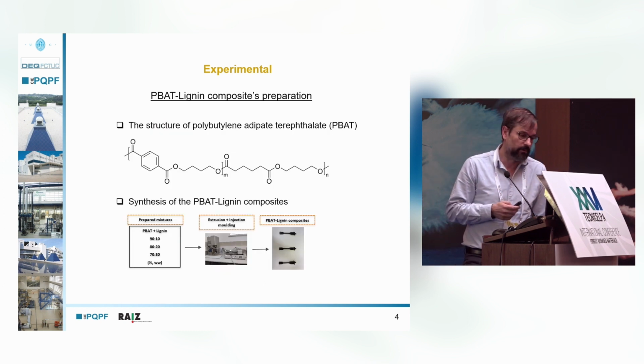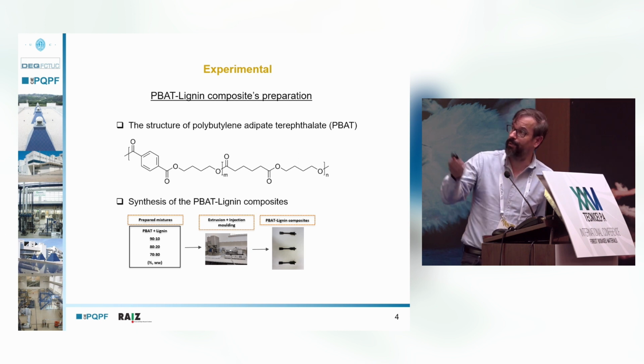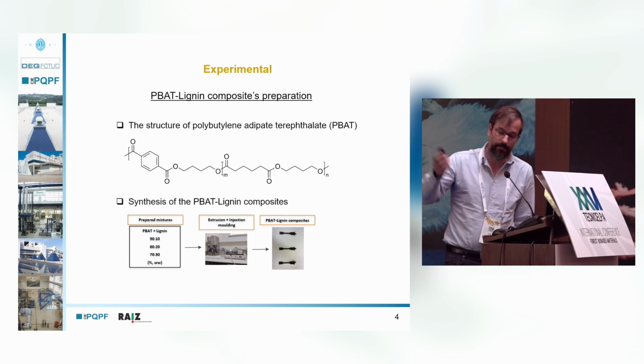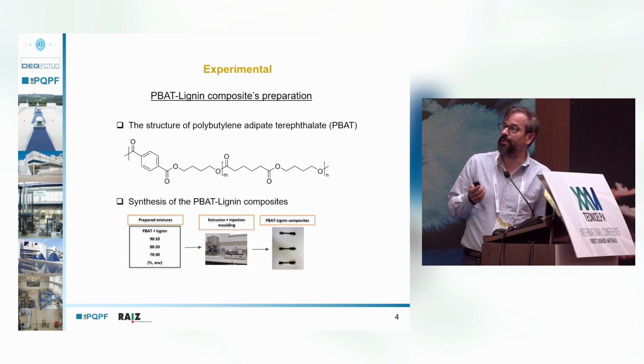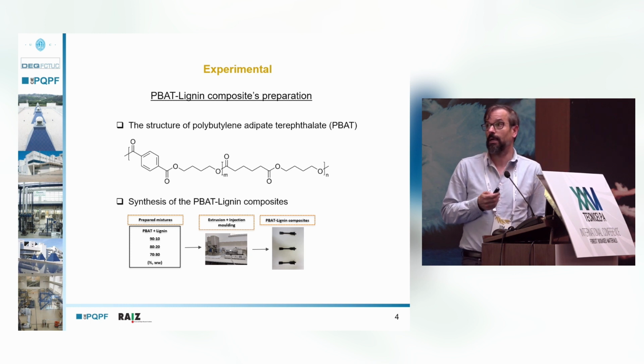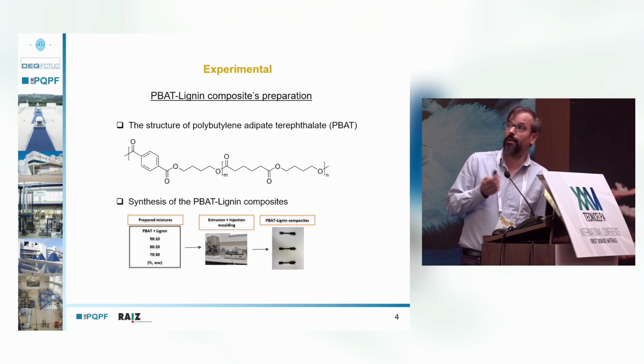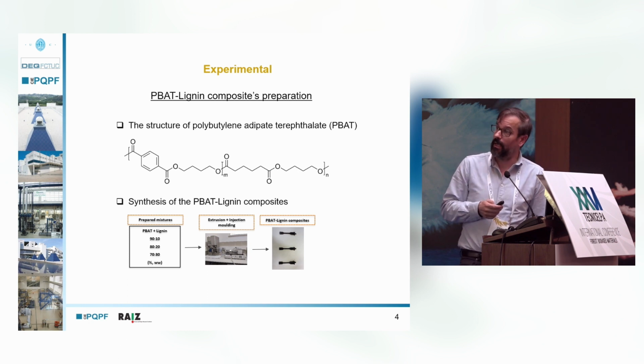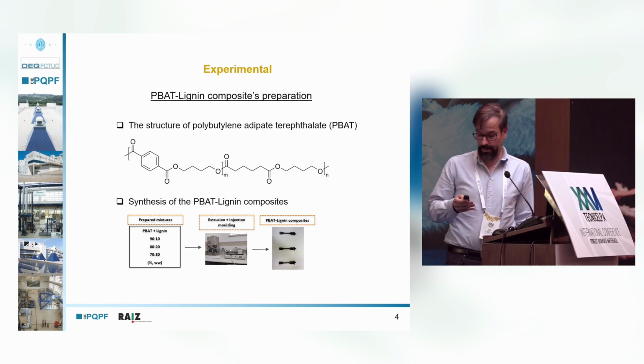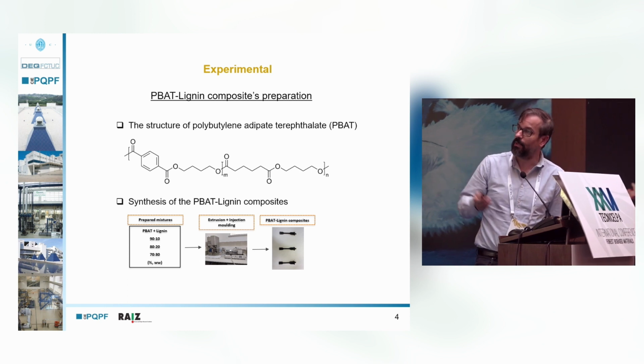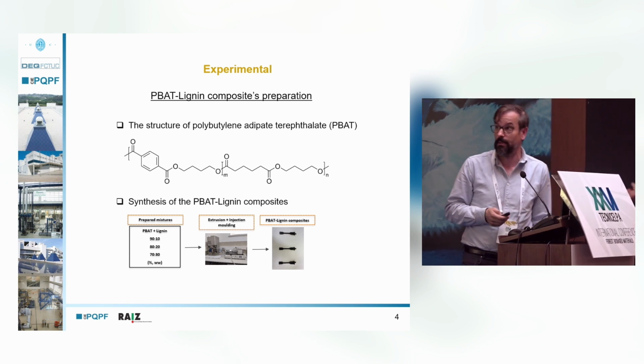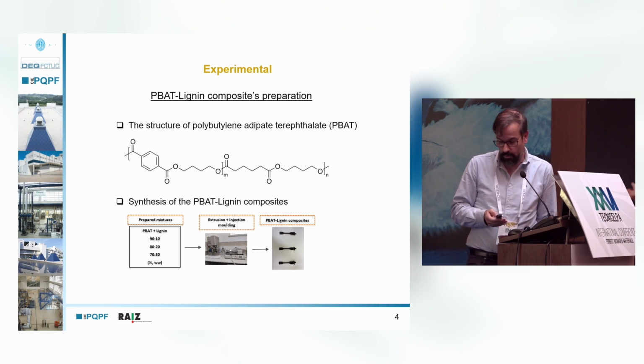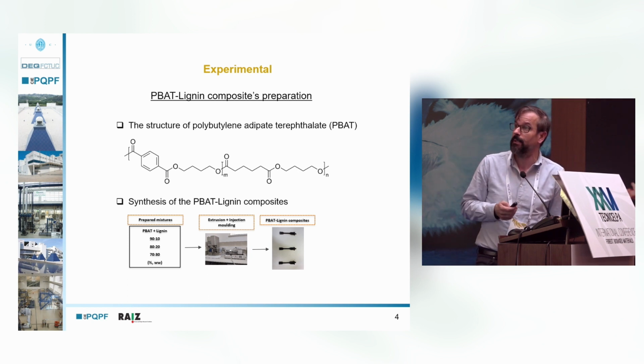The second part of the experimental section is the preparation of composites with PBAT and lignin. The structure of PBAT, which corresponds to polybutylene adipate terephthalate, can be seen in the picture. PBAT is a polyester, a copolymer of butanediol with adipic acid and terephthalic acid. So it has one aromatic part, as you can see, and one aliphatic part. And the aromatic part obviously could anticipate a good compatibility with lignin.